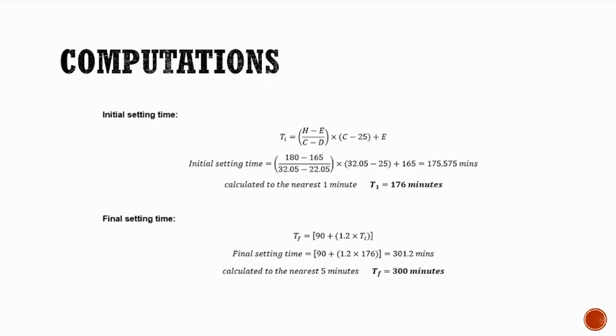So by using the formula, based on the data given, our H will be 180, our E is 165, over C, which will be 32.05, minus D, which will be 22.05. It will now be multiplied by C, which is 32.05 minus 25, and added to 165, which is our time in minutes of last penetration greater than 25 mm. By using our calculators, it will be 175.575 minutes. So based on the C191, it should be rounded to the nearest 1 minute, so therefore it will be 176 minutes.